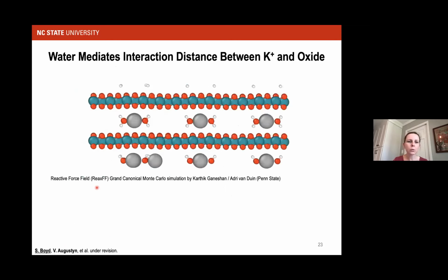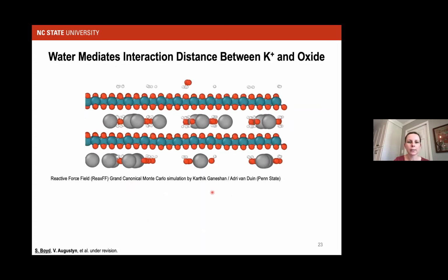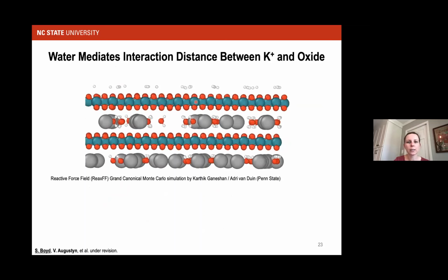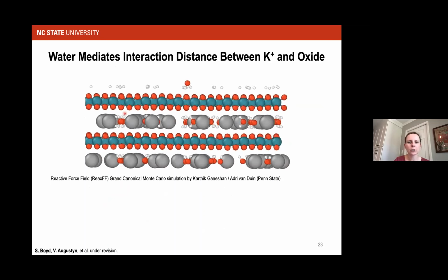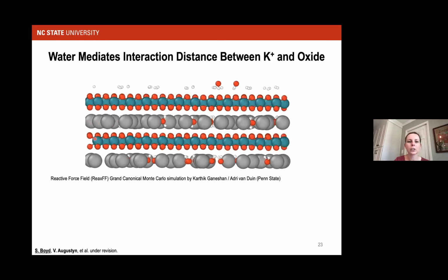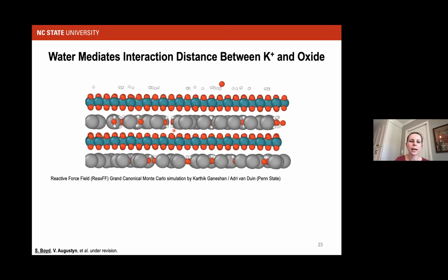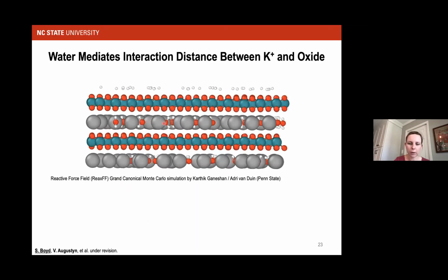So what we think is happening here that's very special for birnessite is that water is essentially mediating the interaction distance. And to get this atomic scale picture, we really can't do it experimentally. This is coming from a reactive force field grand canonical Monte Carlo simulation by Adri van Duin's group at Penn State. So I'm going to play this image for you. So the green is the manganese, the red is the oxygen. So these are the oxide layers. And here's the interlayer as potassium and water begin to populate the interlayer.